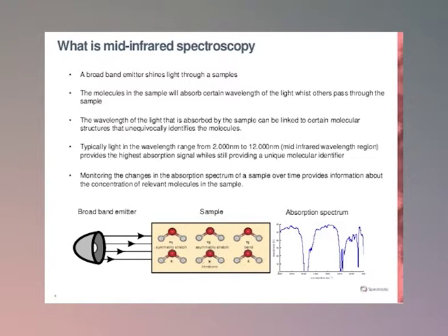Despite this, both the techniques have advantages and disadvantages which decide whether one or the other technique is preferred for specific applications. For example, the presence of water or hydrated chemical species in specimens can hamper the mid-infrared analysis, while the dependence of the Raman effect upon molecular polarizability, rather than the dipole moment as for the infrared, means that polar groups such as OH and CO are better seen in the infrared spectrum, whereas the homopolar groups, that is C-C or N-N, are better seen in the Raman spectrum.